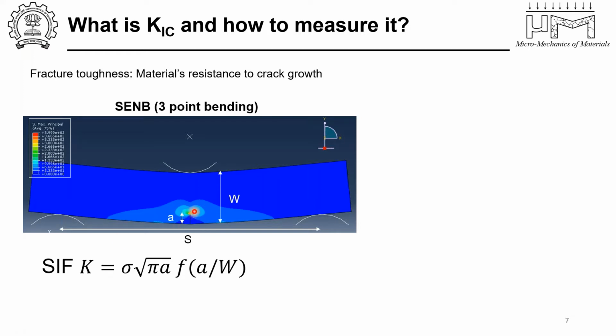The stress intensity factor is basically telling you the strength of the singularity in front of the crack tip, because if you can see here from the stress contour of the FEM model, the maximum stress concentrates in front of the crack. But not only that, there is a singularity that emerges in front of the crack, and the amplitude of the singularity is given by what's called K. So if you see, there is another factor here that comes up, which is called the geometric factor, or what can be called the normalized stress intensity factor. And that refers to the strength of the geometry in concentrating that particular K in a particular way.